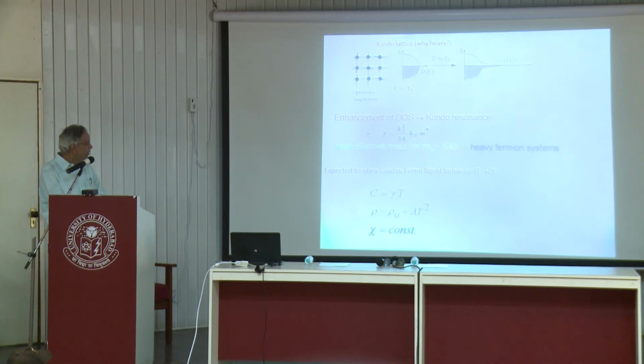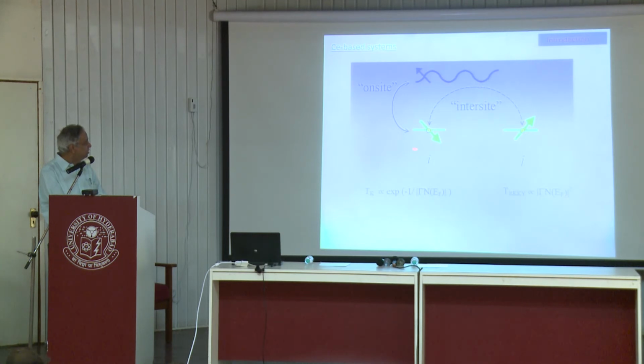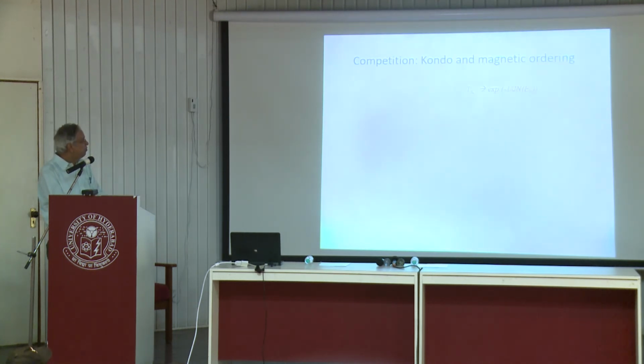So these people are trying to play with this, and you find that one is called the on-site interaction, on the same site, and the other one is the inter-site interaction. Both have different functional forms. The on-site interaction has a functional form like this. This is the interaction strength at the same site, with the density of states. The other is the interaction which is responsible for magnetic ordering, and it goes like the interaction strength squared. So both have different functional forms, and therefore if you have different rare earths, a periodic lattice of rare earth ions in a compound, you will find that there is a competition between these two, and the net result is you have this very interesting phase diagram.